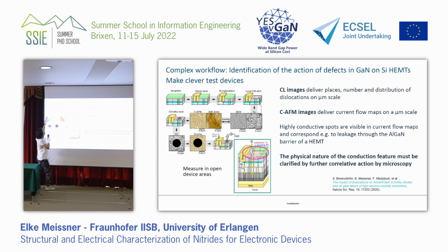So what we do, we create a sample which we observe as-grown, and then we say, okay, we do everything until the ohmic level and so on. And then we locally etch the silicon nitride away, and we have an open area. And after all of the temperature budget and processing, we observe what I described before, locally at such places.